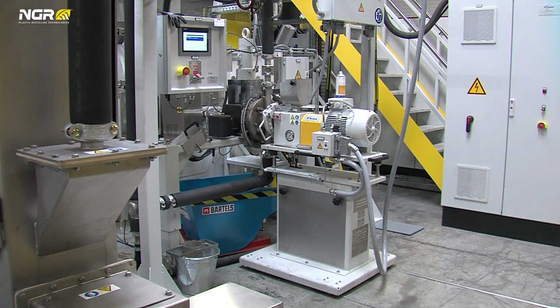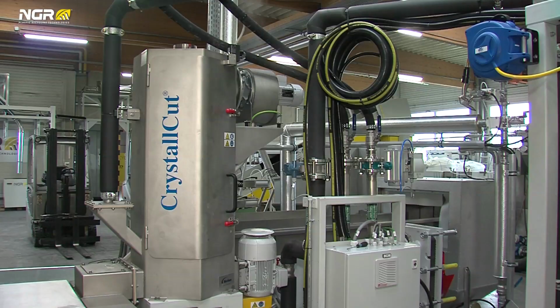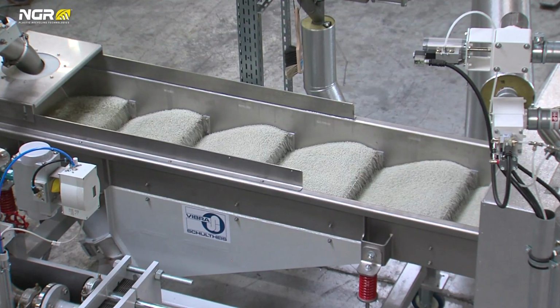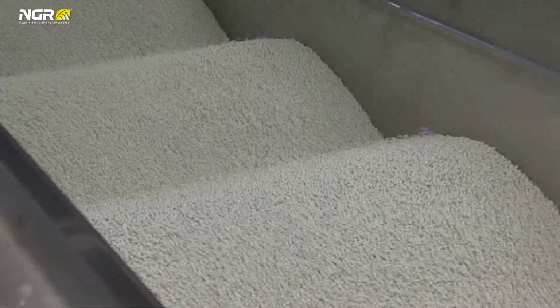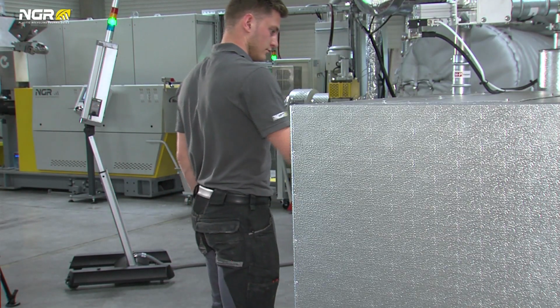The PET pellets coming from the centrifugal dryer enter the crystallization channel in an amorphous state. In a couple of minutes, the pellets are completely crystallized along the vibration channel. The pellets are in a spherical shape and fit the size according to customer or brand owner specification. These are first-class decontaminated and homogenized food-grade pellets coming out of the liquid state polycondensation process.